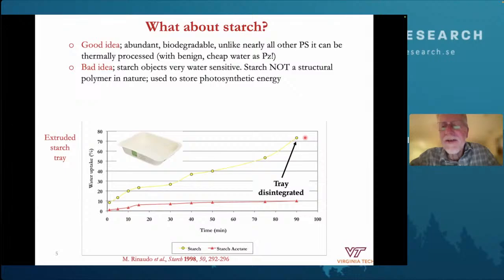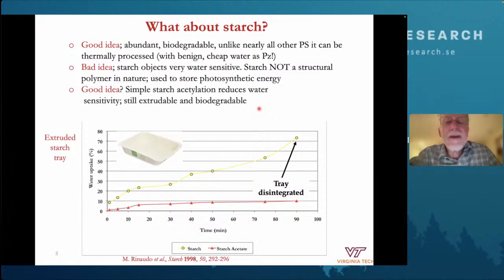They put water on that tray, and your yellow line here just shows the tray literally disintegrated. The time frame here is minutes, right? So over an hour to an hour and a half, the tray completely disintegrated because it's so water sensitive, which would not be a good property for use inside of a fast food restaurant, right? You don't want your tray disintegrating while you're on the way over to the trash bin. But maybe it's a good idea, right?